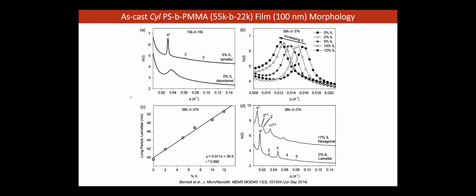So why do we want small molecular weight block polymer? Well, if you want to have very high density of pores, the smaller the cylinder pore size, this would be one way to do it. But if you look at higher molecular weights, like 38K, you can see the lamellar period, this is now lamellae. Bennett did some really excellent work, and he showed that the lamellar period can be tuned from 40 to 50, which is significant.